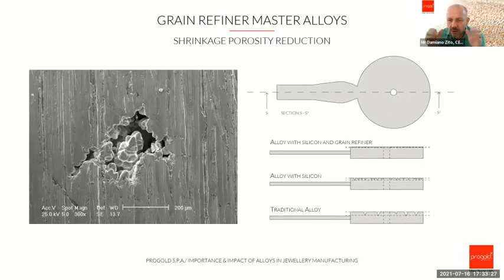many grains start growing, and you have that volume distributed in many small pores. Let's say the volume is 1 cubic millimeter in absolute value. Instead of having 3 or 4 pores of 0.25 cubic millimeter each, you have 100 holes of 0.01 cubic millimeter. It means that the holes are less deep, and when you go to grinding, they are easy to remove without spoiling the shape of the jewelry.